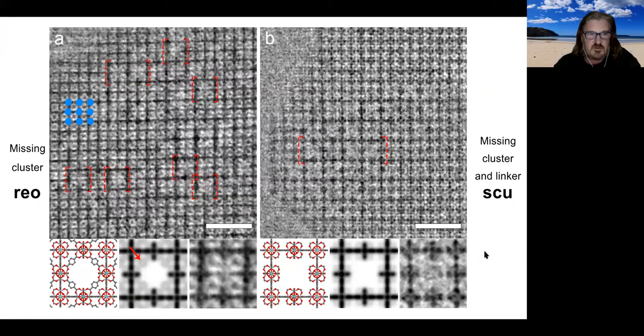But it gets more complicated because there are other types of nanophases within the structure. One is based on what's called the reo topology, after rhenium trioxide, and that's basically where you have a missing cluster. Within this image, these blue spots highlight where we would expect to have these polyoxometalate clusters. If I draw your attention to these red bracketed regions, there's a spot here, a spot here, a spot here, and so on, but there's no spot in the middle, and that's direct evidence of a missing cluster.